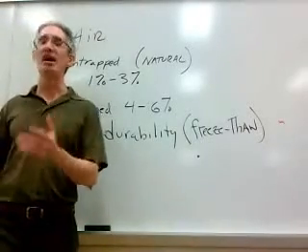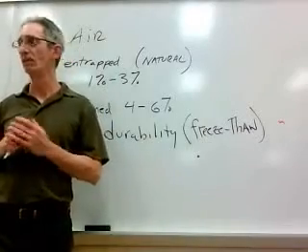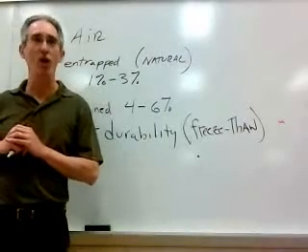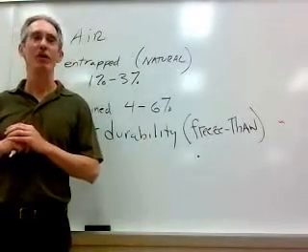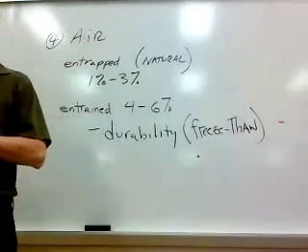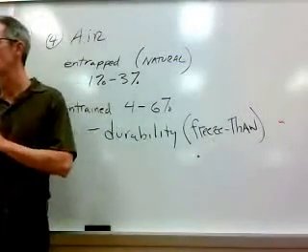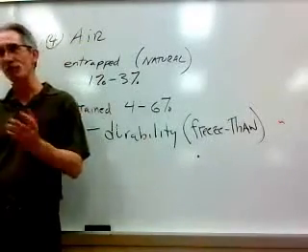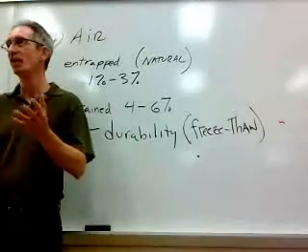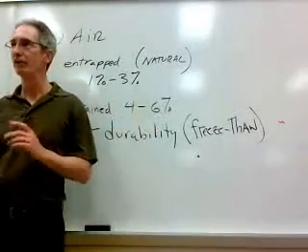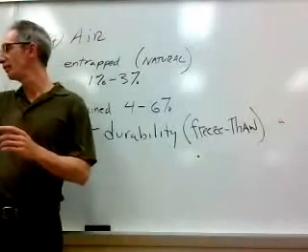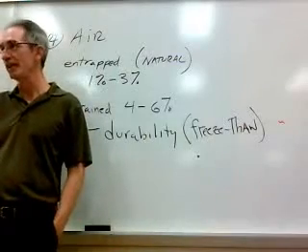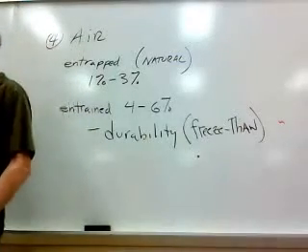If that concrete's subjected to freezing weather, what's going to happen to water molecules? They're going to freeze. Water gets bigger when it freezes and turns to ice. What's it going to do to a hardened mass of concrete? It's going to crack it. And that cracking, maybe the first crack, a little micro crack, is not a big deal, but that takes place 100 times a winter. And all of a sudden now you're 10 winters into the concrete life. All of a sudden now that concrete's really starting to deteriorate.